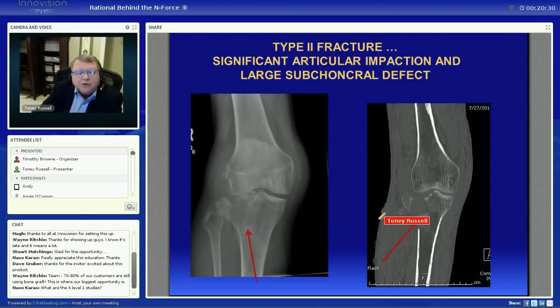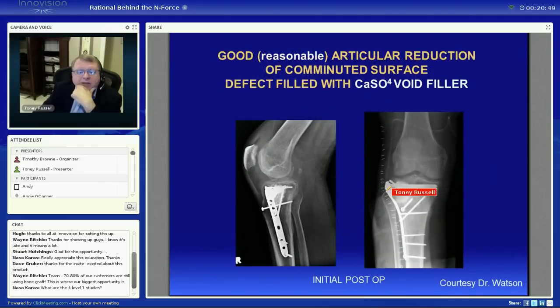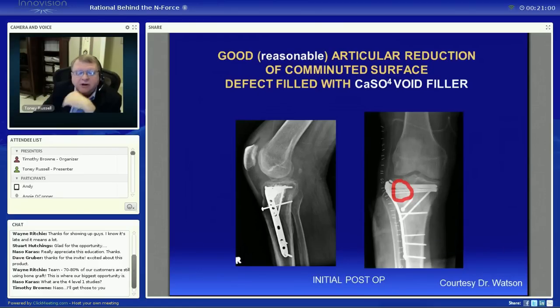Early on in the 1980s and 90s, we were starting to play with calcium sulfate, which is plaster of Paris. And this is a tibial plateau. You can see here's a big defect up in this area. You see, that's a big old hole. This is the articular surface down here. So that's how far it's been pushed down. So Dr. Watson gave me this case. So he reduced it nicely, and you see this white material right here is calcium sulfate that he put in there. So it looks pretty good.